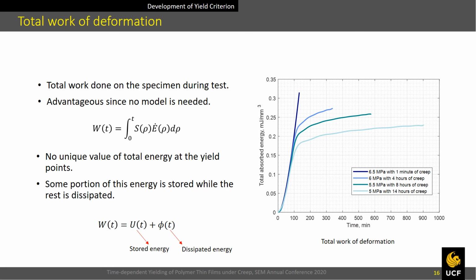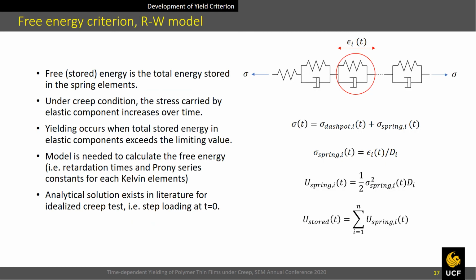It might be useful to explore stored energy in the specimen, which leads us to a second energy criterion to be explored. The second energy criterion investigated is the free energy approach. Free or stored energy is the energy stored elastically in the material. Under the creep condition, the stress carried by elastic components increases over time. It was postulated that yielding occurs when the total stored energy in the elastic components exceeds a limiting value. For this criterion, the calibrated model is needed to calculate the free energy.